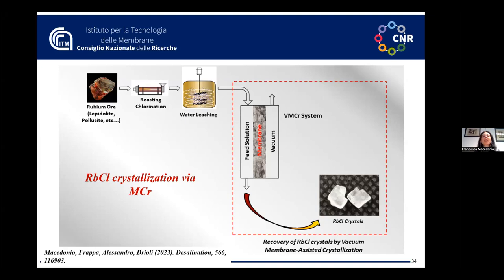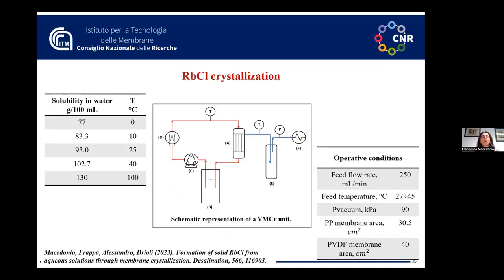Yeah, okay. Also here, the first step was to find the best configuration and operative conditions in the membrane to achieve the crystallization of rubidium chloride. Like in the previous case with lithium chloride, we tested the various possible membrane crystallization configurations, but again the only possible configuration is the vacuum one, for the same reason: to have a higher driving force due to the very high solubility of this compound.